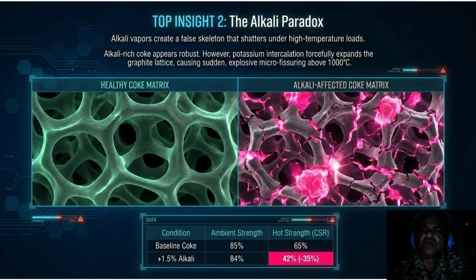In our next slide, which is about top insight two, that is the alkali paradox. This is what I call the alkali paradox. Look at the split screen macro photography. On the left, the healthy coke matrix shows a robust emerald green cellular structure. On the right, the alkali affected matrix is riddled with a myriad of micro fissures. This is the trick: alkali rich coke actually appears robust at ambient temperature, but as it descends and hits that 1000-degree mark, the potassium intercalation forcefully expands the graphite lattice. It creates a false skeleton that shatters the moment it takes a high temperature load.